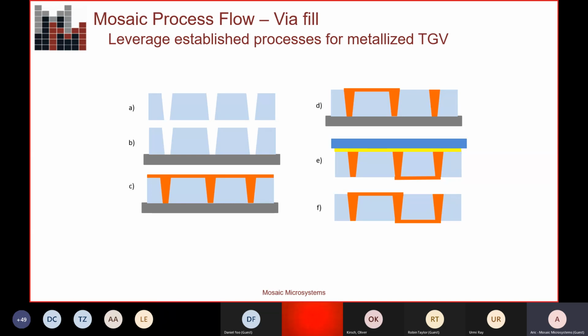And then there are paste solutions, but if you have a low temperature paste, you tend to have issues with conductivity and perhaps outgassing. High temperature pastes tend to have a high sintering temperature, and then the CTE mismatches cause an issue. All of these things have been done over the past decade, and what we're trying to do is make this look like a silicon wafer as much as possible, so that we can leverage wafer level metallization strategies to really enable high volume capability.